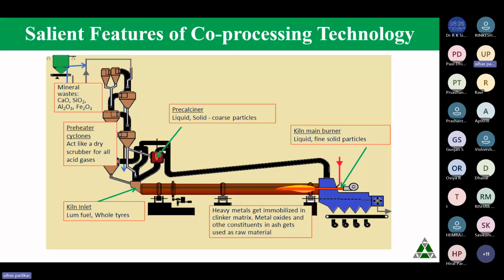So we will be feeding the waste material or the FRP or SMCs into such cement kilns, which have that giganticity. The temperature here in the flame is about 1800 plus degrees centigrade. The residence time of the gases in this kiln will be about 6 to 10 seconds. Normally, when we design any incinerator, the norm is 1100 degrees centigrade and 2 seconds residence time. Here we will have up to 1800 to 2000 degrees centigrade, and the residence time will be 6 to 10 seconds. In terms of residence time, it is maybe 3 to 5 times more than what the incineration design demands, and the temperature is almost double. So that's the intensity this particular cement kiln has got.